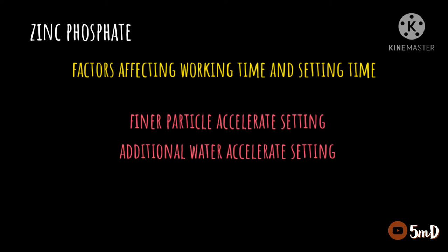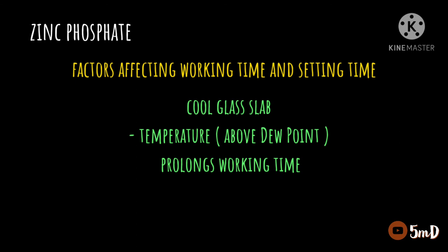To prolong the working time, we use a cool glass slab. However, the slab temperature should be kept above the dew point so that condensed water does not interfere with the setting reaction. When the slab is cool, the exothermic reaction heat is dissipated, which prolongs the working time.